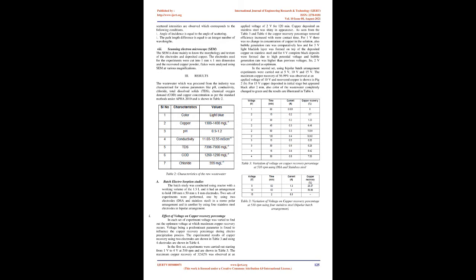Chloride is analyzed by the argentometric method. The reagents used for this analysis are silver nitrate solution, 0.0141 N, and potassium chromate indicator. Take 25 ml of sample in a conical flask and add 2 to 3 drops of potassium chromate indicator. Titrate against standard silver nitrate, AgNO3, to be consistent in endpoint recognition. Color changes from yellow to pale brick red. Chloride content of the wastewater is calculated.